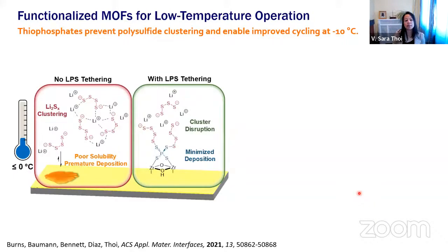Finally, I want to talk about one more thing about these MOFs. We were interested in trying to use our MOFs for low temperature battery cycling. And one of the key issues in lithium sulfur batteries at low temperature is that we start to see the polysulfides that are generated start clustering around themselves, where the sulfur much prefers to interact with the lithium than with the solvents that it's in. This clustering leads to poor sulfur accessibility and then eventually some premature deposition that causes our batteries to fade at low temperatures. So we thought, well, if we have these thiophosphate functionalized MOFs, can we use them to disrupt the clustering formation that happens at low temperatures, thereby minimizing this deposition process?